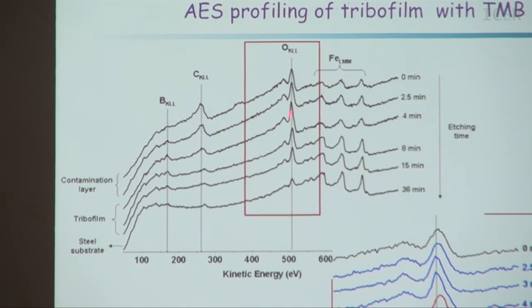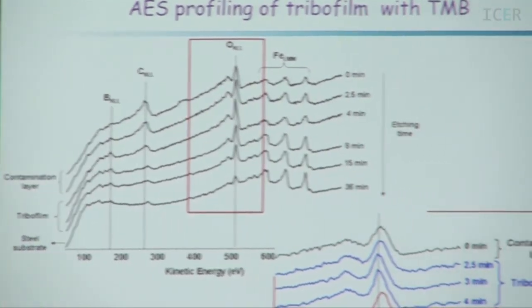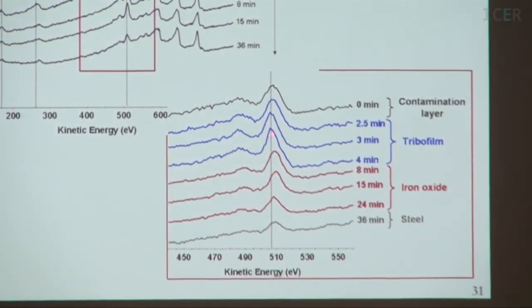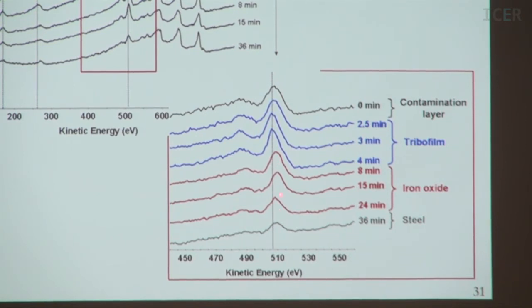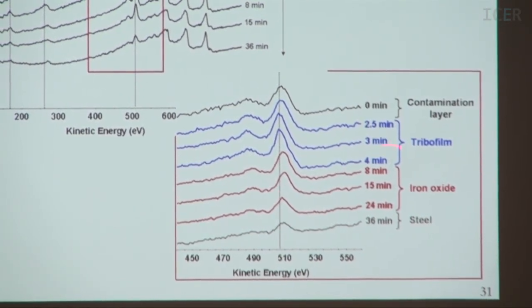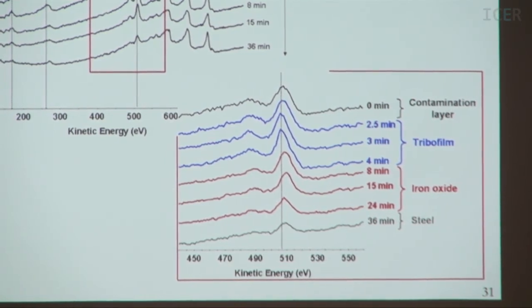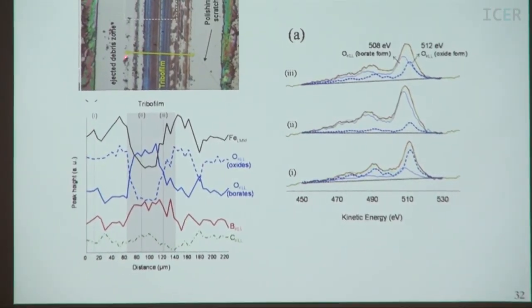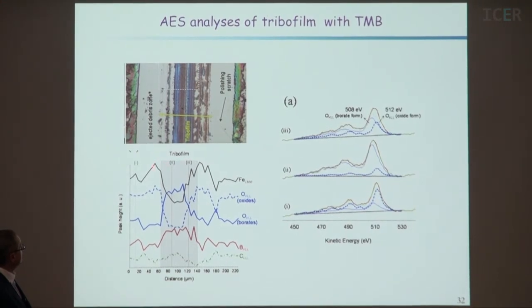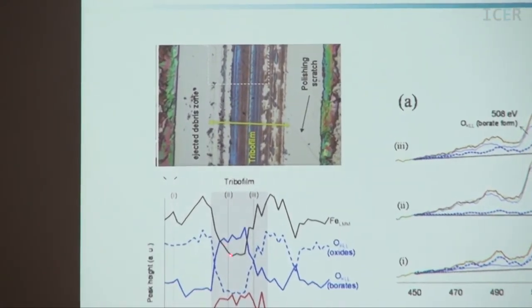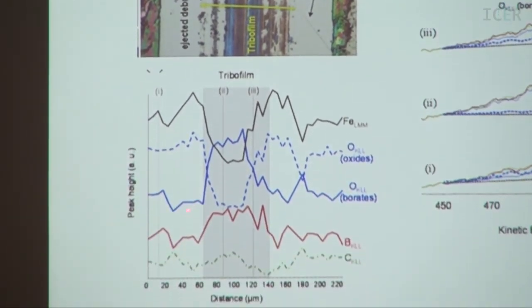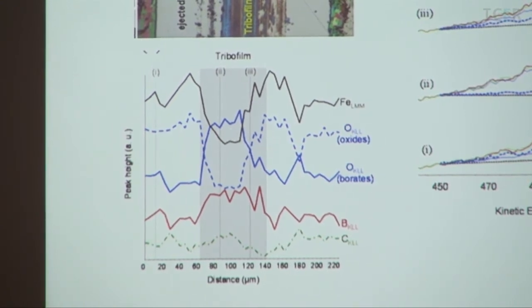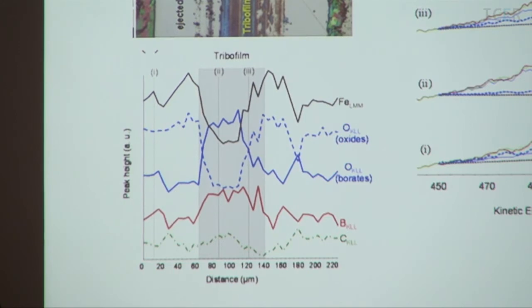But if you look carefully at the oxygen peak here, you have different forms of oxygen. You have the tribofilm, which is here, and you have the iron oxide, which is below. So the borate is at the top, and the oxide is below. This is because there is a chemical shift in the energy of this peak, and we can recognize the oxide from the borate. So if we have a profile like that, we can see that in this wear track we have less iron, we have borate, less oxide, and boron. So typically, we were able to see the reaction of the borate with the oxide.